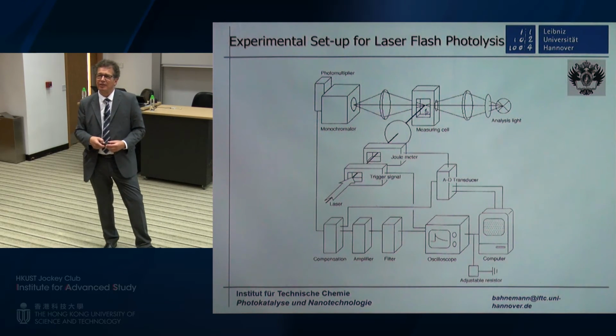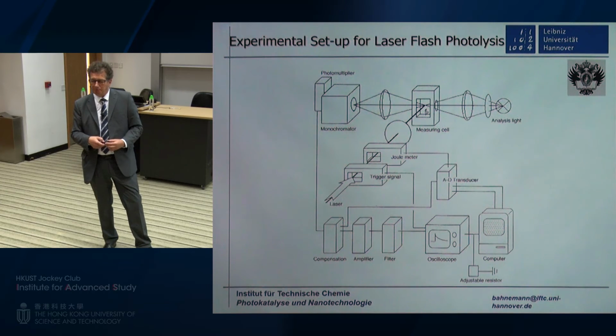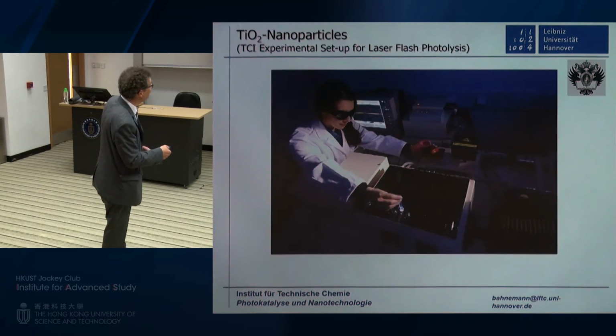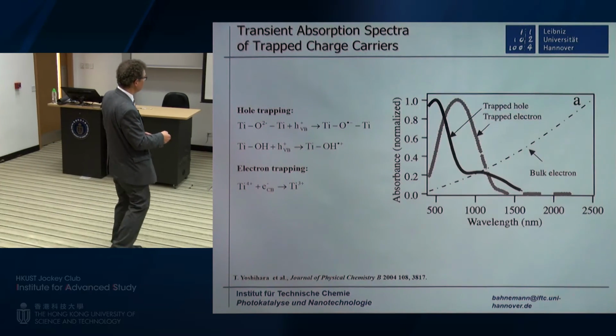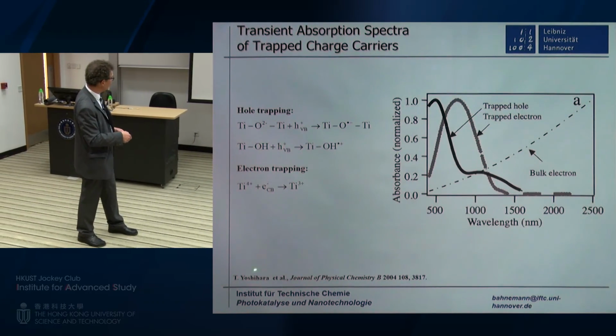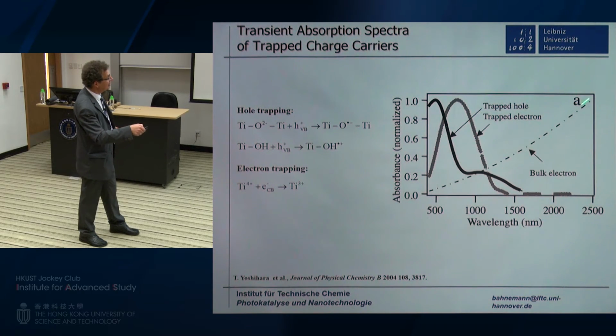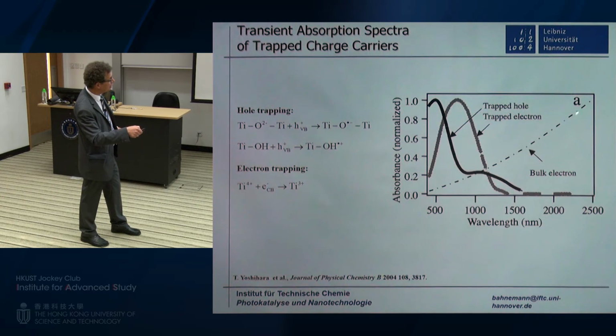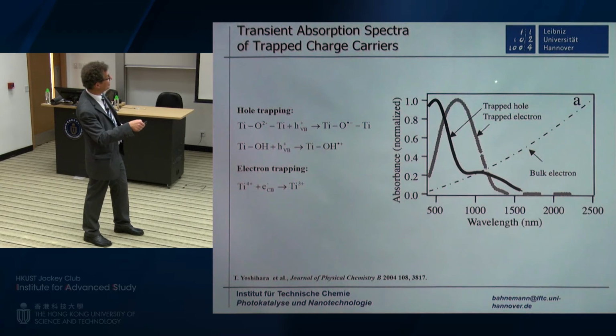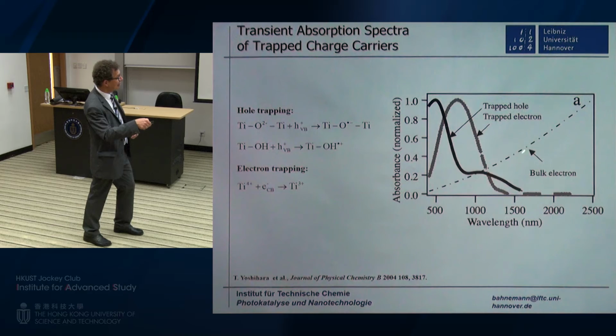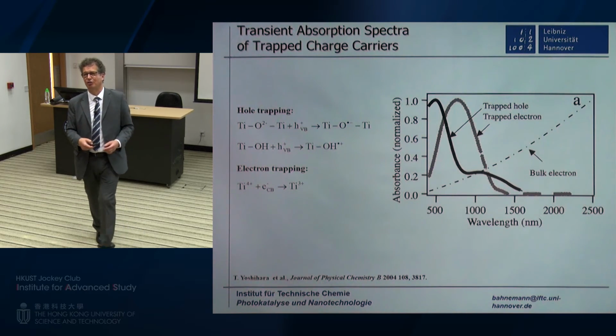So generally, if your electron is not trapped by the titanium ions itself, you cannot observe it, right? This depends, because this is what you find in the literature. This nice review of Yoshihara, he took data of whatever group, showing that the bulk electron, the non-trapped electron, should lead to a transient absorption. This is normalized. You should not take it for granted that it's the same height. So it's pretty small, but they have seen transient absorption above, let's say, 1500 nanometers for the bulk electron.